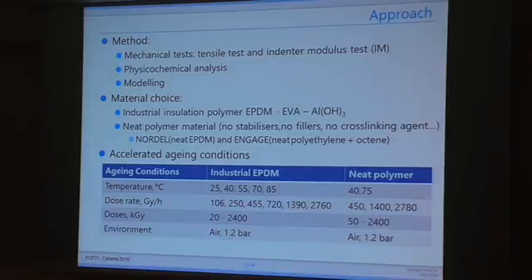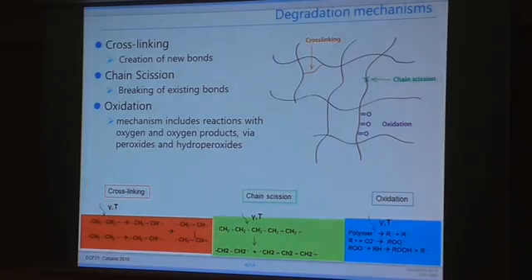So we performed accelerated aging, and we varied temperatures, dose rate, which is irradiation flux, and also doses, which means the irradiation flux multiplied by the time that the sample was under the irradiation conditions. We especially focused on varying dose rates because we want to study the so-called dose rate effect that I will explain to you a bit later. So before I start to talk about the results, I would like to mention the main degradation mechanisms that affect polymers.